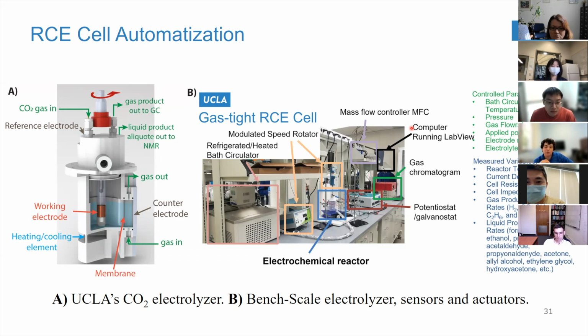The same goes for the current distribution in a rotating disk. It's actually not uniform. You have very high currents at the edge of those disks, while in the cylinder, the current distribution is actually very homogeneous. And this was described by Newman in the 60s and 70s, and then it was a hot topic, using rotating cylinder electrodes. I don't know if you have learned electrochemistry with Newman's book, but we were surprised to find out that in one of the chapters, the paragraph says that people should drop the rotating disk and use the cylinder because of all those challenges. So the cylinder is actually quite good. We did not know. It was by chance that, for different reasons, we decided to use a cylinder. But now we understand